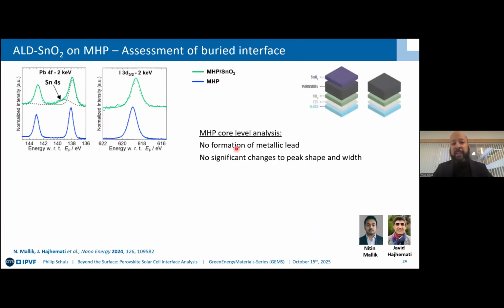Now, looking at the different core levels, I'd like to walk you a little bit through how I want to present these things. You see here on the left-hand side the lead 4f core levels, and on the right-hand side the iodine 3d core levels. And blue is just the perovskite, and green is the perovskite with this nominally 5 nanometer thick tin oxide film on top. And what we already see is there is no formation of metallic lead, and as it seems no significant change to the peak shape and width. And this led us to believe, well, maybe there is not much to see in terms of defects after all.